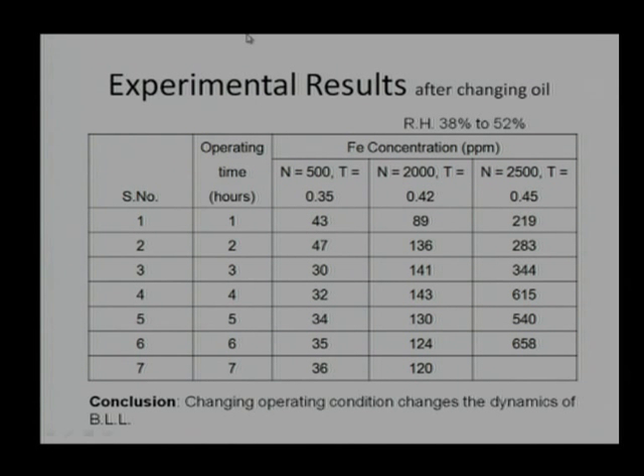Okay, so before that, the conclusion from this slide: changing operating condition changes the dynamics of the boundary lubrication layer. It is continuously changing, it is not stationary. At 500 RPM, it is showing a steady state condition, but when you are switching to 2000 RPM, it is showing a high wear rate. As I mentioned, one possible reason is vibration, continuous periodic loading, and that is going to induce fatigue failure in a surface, or at least the top asperities are chopped off. So, we need to confirm that with a load. If I increase the load, what is going to happen?